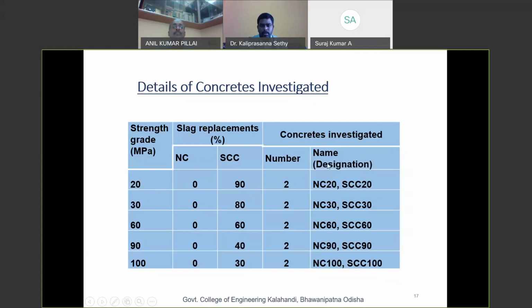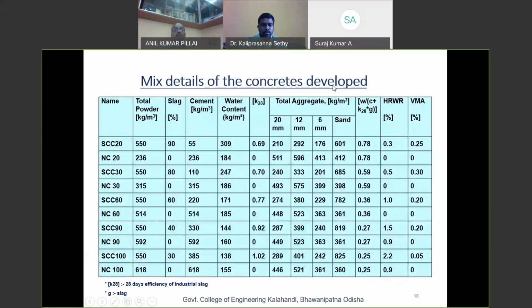And the concretes developed here are designated as NC and SCC. And these are the mix details of the concrete developed. From this you can see the total powder content. For all the self-compacting concretes, it is fixed to 550 kg per meter cube. And this is the slag percentage, cement content, water content, K factor, efficiency factor, and based on this efficiency factor, we have calculated the water cement ratio for this design purpose.